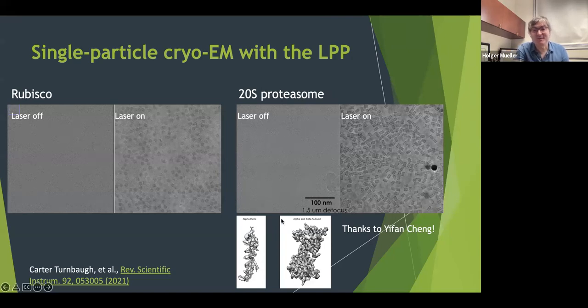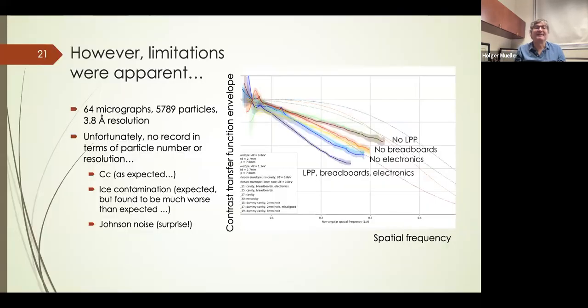From these images, we performed a complete reconstruction of these proteasome particles, and we're quite happy. That happened about 2 years ago. But limitations were apparent. Unfortunately, these reconstructions do not represent a record in terms of particle number or resolution or particle size or what have you. What are the reasons for these limitations?